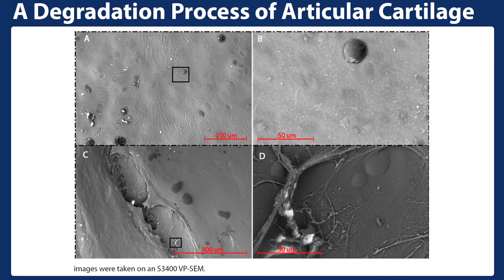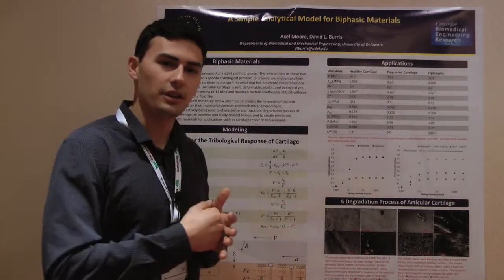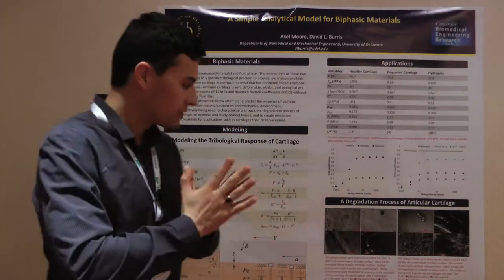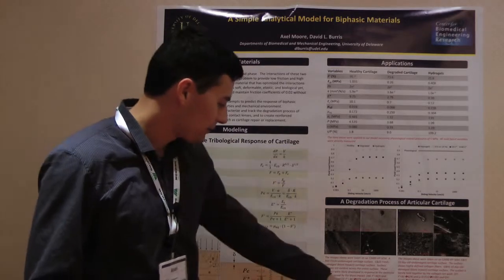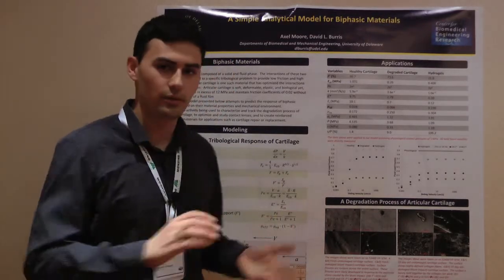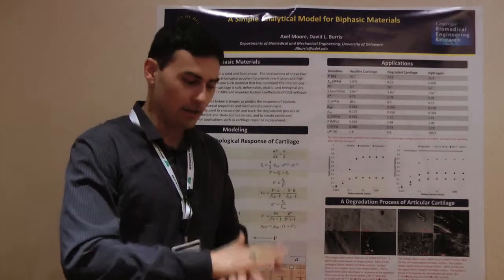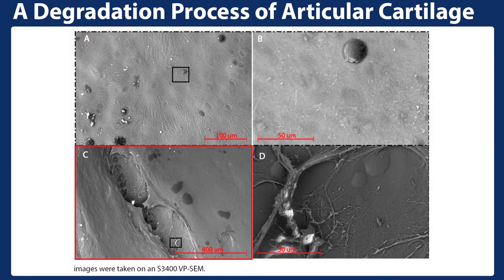Here I show a degradation process through electron micrographs. Healthy cartilage looks pretty unremarkable under a microscope — basically a blob, nothing unique. But if you apply a blunt impact injury — like the high loading from a car accident where joints get heavily compressed — surface fissures form. The collagen network that maintains the tensile modulus fissures just at the surface layer, breaking down your fluid load support. Just a surface fissure takes you from 86% fluid load support to about 82%, without roughing up the surface at all — just fissuring it degrades that E* property.